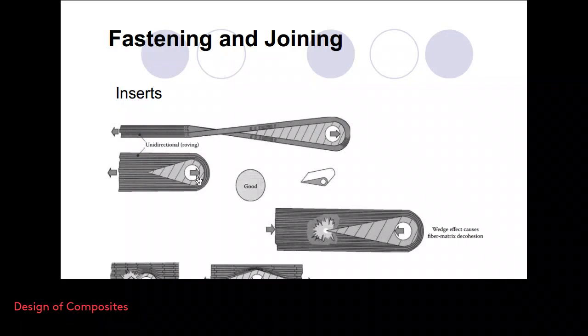So you have a sharp V-type groove and you gradually change the thickness of the laminate from a certain desired thickness to a lower one, and as a result the fibers will be subjected to a tensile force. Of course, when the force is reversed, so you have a compressive force, for example, it is not a good idea to use such an insert with a sharp corner. Certainly this will cause a delamination.